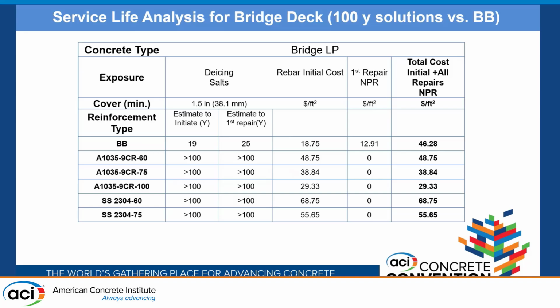And you can actually look at the cost analysis on this. So you can see the black bar is low up front, at 75 cents a pound, but you don't have 1 pound per square foot of bridge deck. So when you actually figure out how much you've got in there, it has a low initial cost compared to everything, but your first repair comes at a relatively early time. You do a net present value cost analysis of what it's worth in today's dollars, and it's $12.91, and you add up all the other repairs you have in that 100-year lifespan, and it ends up being $46 a square foot.